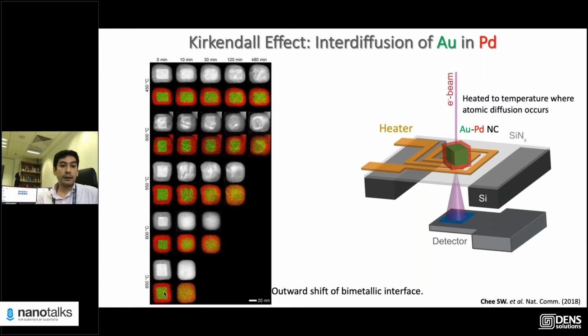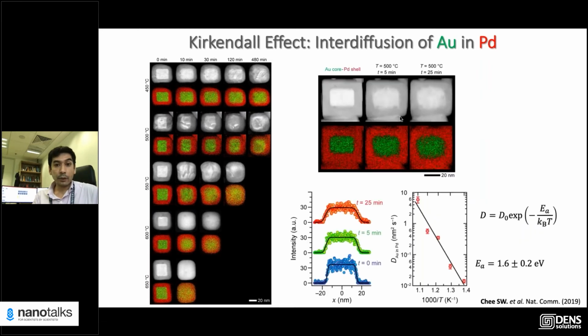So in this case, essentially, gold and palladium are mixing. But keep in mind, palladium is actually diffusing faster than the gold. This is known from the literature, but based on this EDX data from individual nanoparticles, you can actually extract this. What you do is map out a profile of your core as it changes, right?